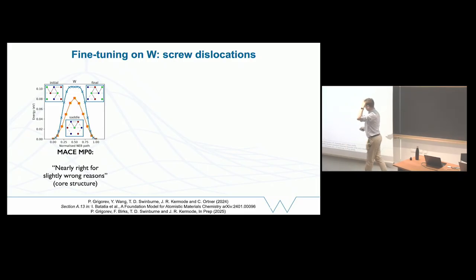If you take the model as it is and you try and apply it for the problem that we wanted, you see this core symmetry isn't quite right. It doesn't quite match the pictures I showed you earlier on. The saddle point actually isn't the right configuration either. But if you squint a bit and only look at the energy barrier, it's not too bad.